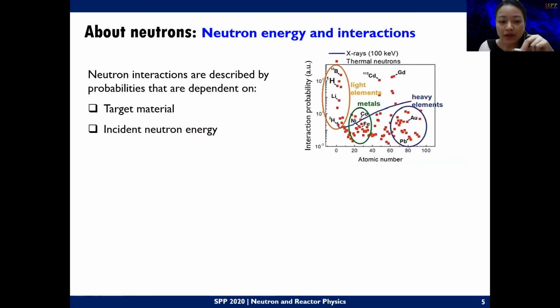Now, neutron interactions are described by probabilities that are dependent on the target material and the incident neutron energy. We have here on this plot an example of how the interaction probability of neutrons varies depending on the target nuclei. But compared to a photon, like a 100 keV X-ray, which has a very predictable interaction with different materials, we see that there is no simple pattern in the interaction probability with neutrons. In fact, hydrogen 1 and hydrogen 2 are the same element but different isotopes, but the interaction probability with neutrons is very different.